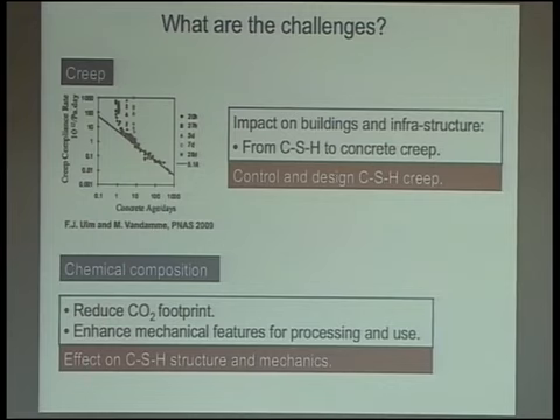But the main reason why there is a lot of interest at the moment in this is because of the CO2 footprint of the material, there is a strong pressure to reduce it. And the forefront of the research at the moment is in trying to devise a new green formulation that would allow producing cement without such an enormous CO2 production. And so this has moved the attention again towards the early stages of the material, when it's still a soft material and when the properties of the gel develop. And although you have already some ideas of how to change the chemistry and reduce the amount of calcium that is basically needed, the problem is still that when you do this new formulation, you don't get the mechanics at the same level that you had before, and this is because a number of features of the gel actually change, and so its mechanical properties change.